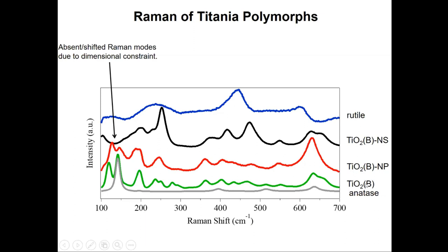So when you have TiO2-B, you can see that at the low frequency range, there's a very discrete set of peaks. If you make a nanoparticle, these peaks mix with each other. But if you have a nanosheet, these modes die out. That is in contrast to when you have anatase present, where you have this one primarily vibrational low frequency mode that uniquely identifies anatase. And then, of course, rutile is another higher temperature thermodynamic form of this that also has a